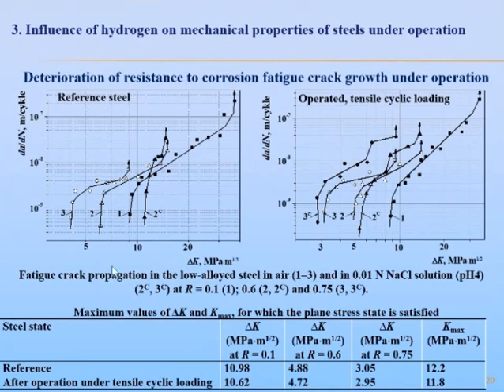And at the lowest stress ratio, 0.1, surface degradation of steel had no notable effect on fatigue growth rate in air. The difference in fatigue growth rate values for the steel in different states was revealed mainly in the near threshold region of stress intensity factor range. And at higher values of stress intensity factor range, the difference was not observed.